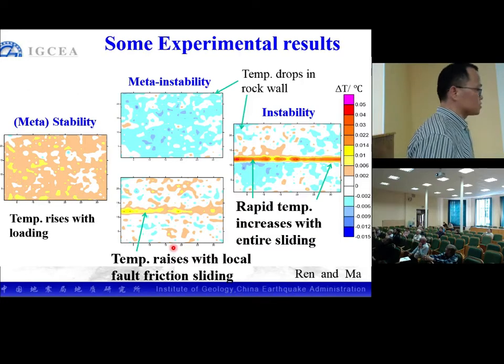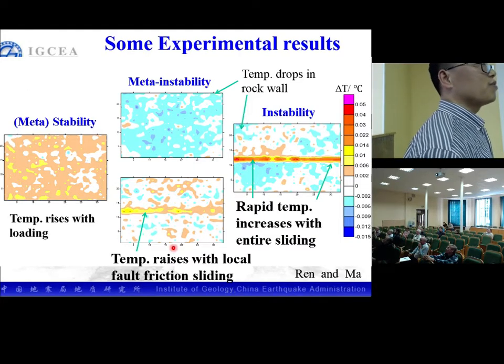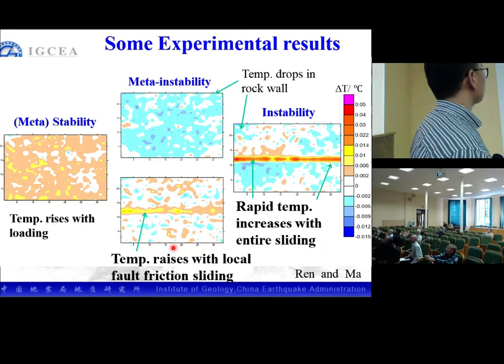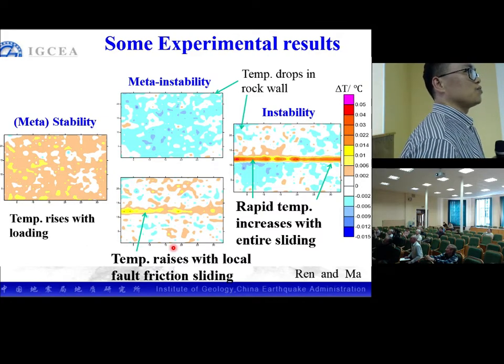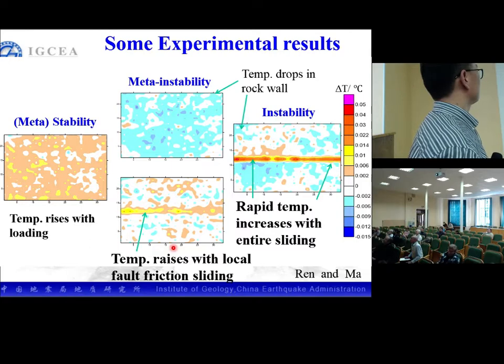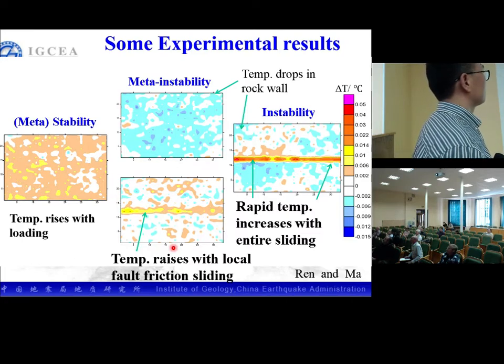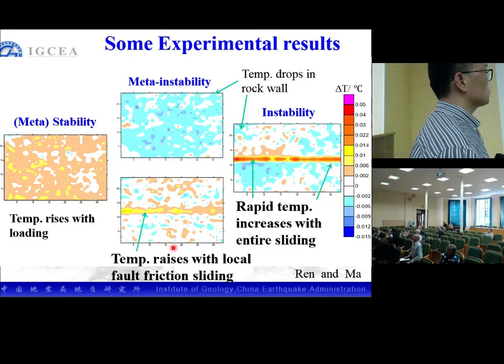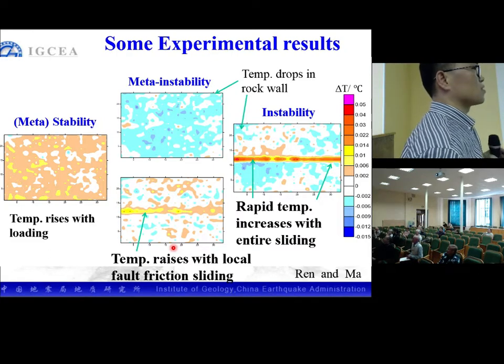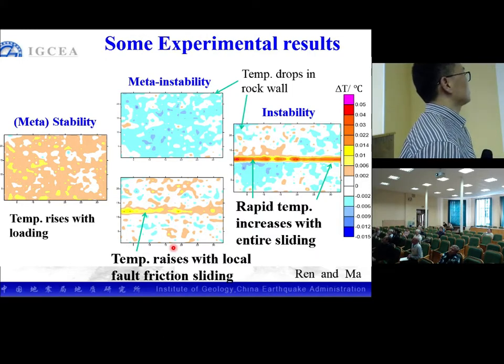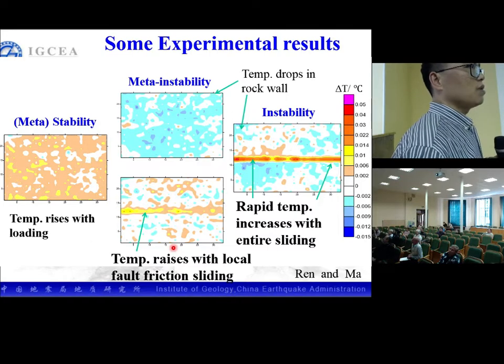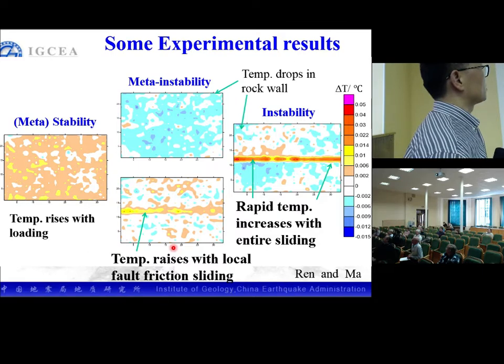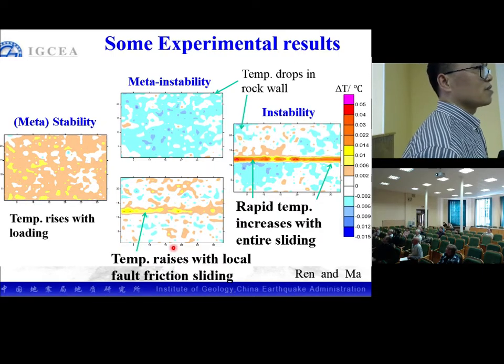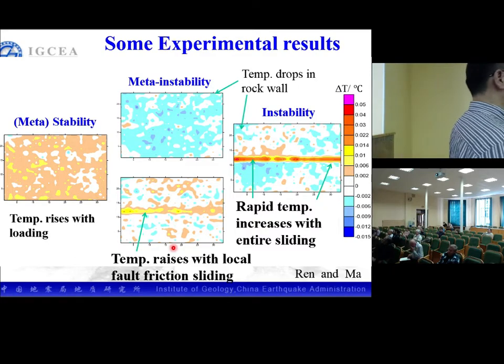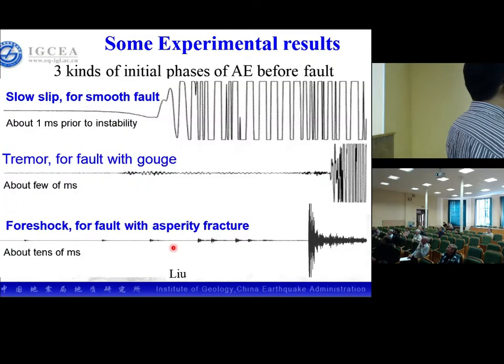This is another result from thermal infrared camera images. We also get the same result: when the loading increases, the temperature rises with the loading, and during the metastable instability, local fault friction sliding can show some temperature change, and during sliding of the whole fault, the temperature increases very fast.